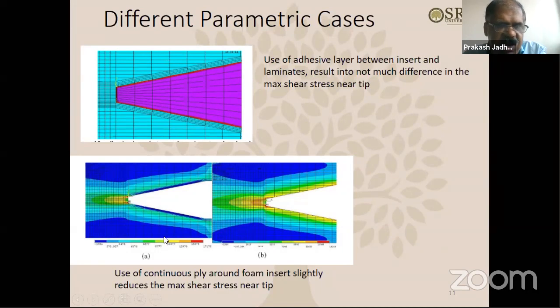What is the definition of continuous ply, basically? If you have a foam insert, and suppose you take a carbon composite ply and wrap it around the foam insert. So it's like a wrapped foam insert, and then you put the foam insert inside the carbon composite. What is the effect of that? Use of continuous ply around the foam insert slightly reduces the maximum shear stress near the tip.